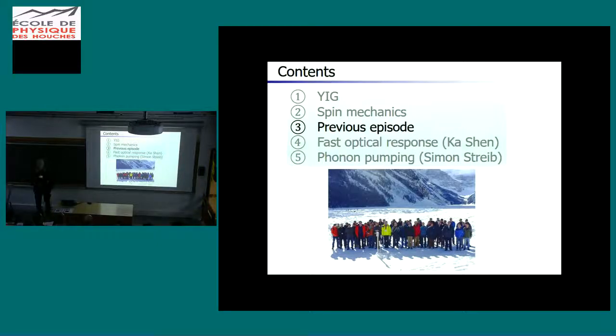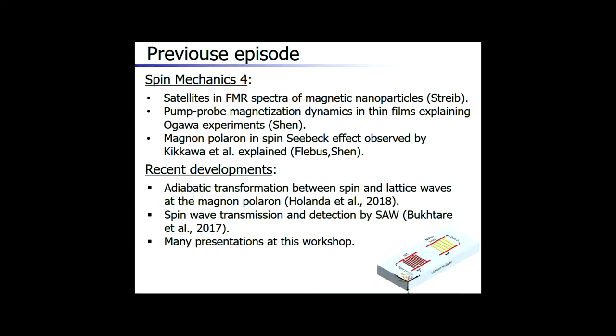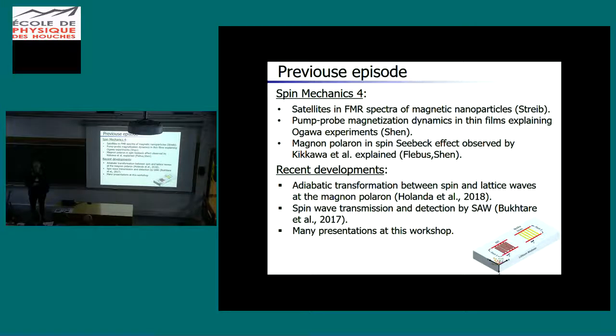Let me just review a little bit about the previous episode one year ago when we had Spin Mechanics 4. At that time I reported results from Simon Streib on the FMR spectra of magnetic nanoparticles, which showed satellites due to the Einstein-de Haas and Barnett effects. Ka-Shen had explanations for pump-probe magnetization experiments on thin films of YIG. I will review it in a second. We will hear more about it from Professor Saitoh, I think, but at that time we had just discovered the magnon-polaron anomalies in the spin Seebeck effect.